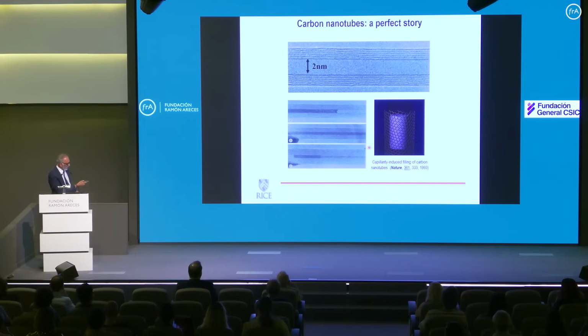So carbon is very special because it hybridizes into sp2 and sp3 hybridization. One forms this layered structure, which is called the sp2 hybridization, forming this hexagonal honeycomb lattice, which is stacked in layers. So to think about this tube is to take a layer of this graphite and then fold it into a beautiful cylinder, completely perfect. In fact, you can see this in this illustration, a honeycomb that has been turned into a beautiful cylinder.